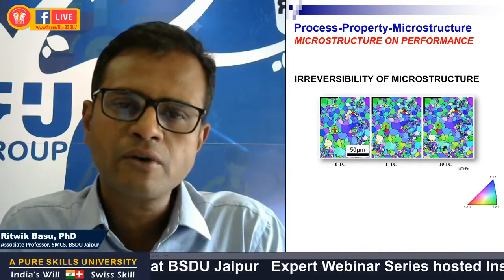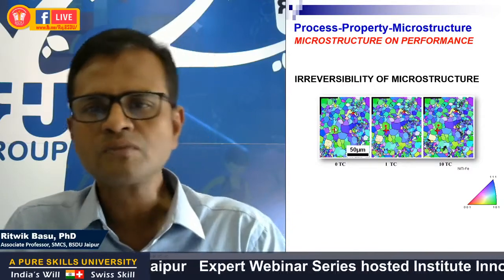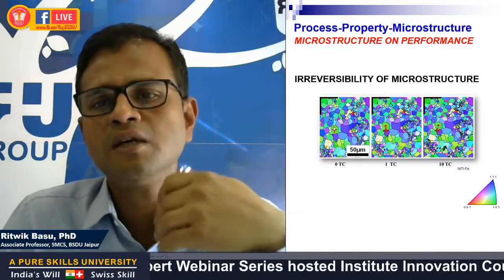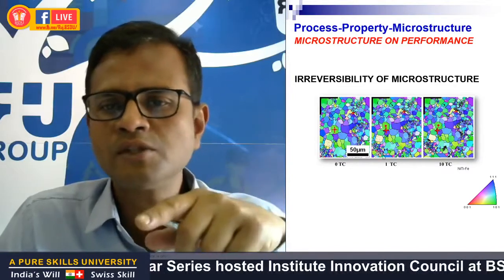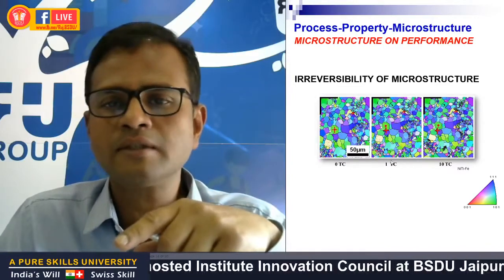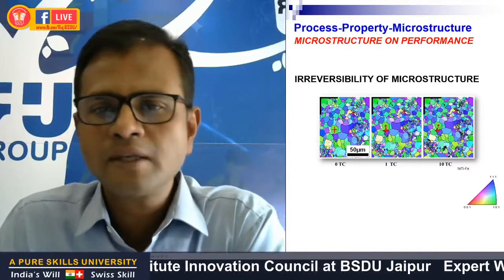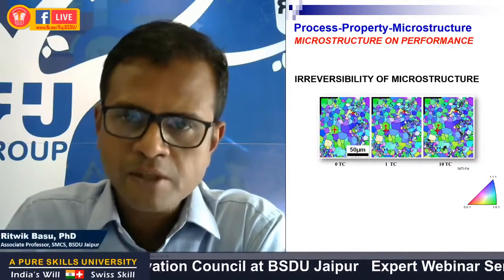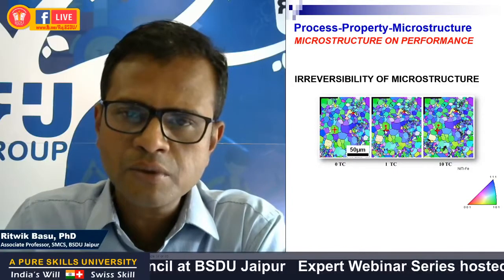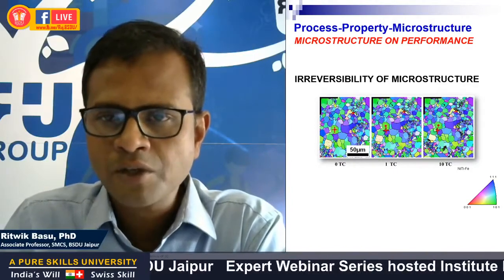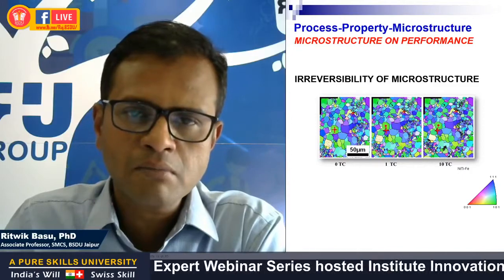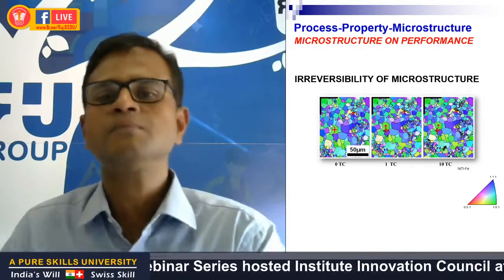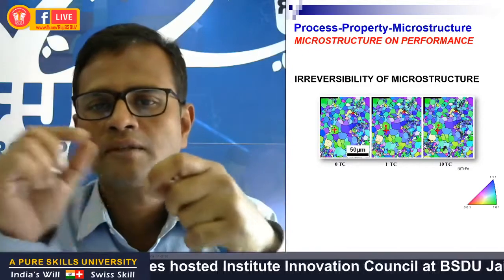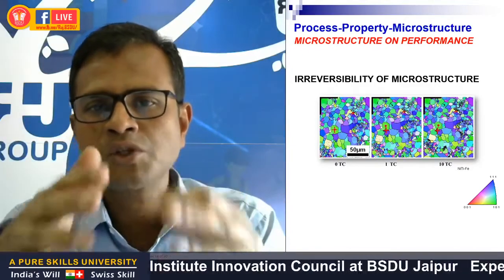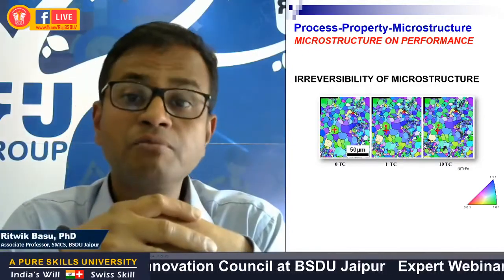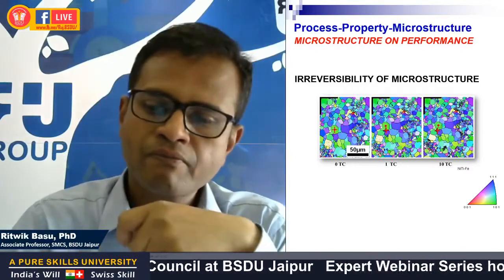We then overlaid a crosshair right on top of the dot. So what we could see after a number of thermal cycles, though for our convenience we have shown the first and the 10th thermal cycles, is that there has been some shrinkage in grains. Some grains have bulged, and that led to a significant displacement of the dot. So basically, this inverted L and the crosshair can be assumed to remain fixed to a reference, and the dot is a movable thing. So there is a clear signature of microstructural irreversibility.